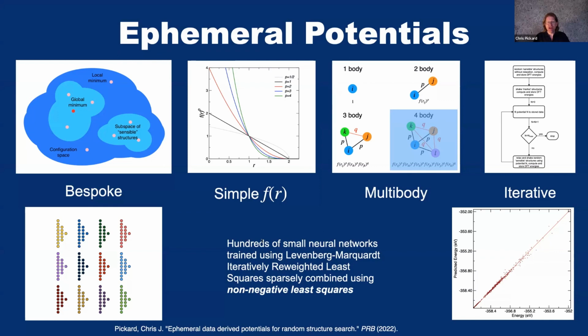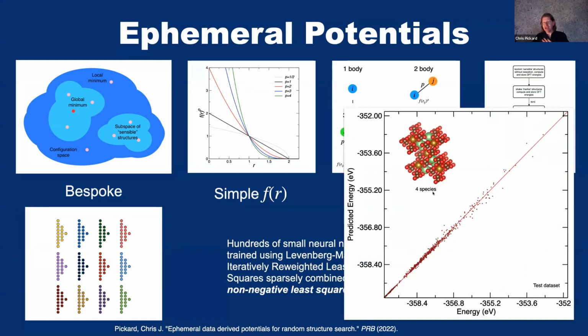And there are some details here of how we've done this. Those that are interested could read those words. They won't necessarily mean something to everybody, but we've made lots of small choices to make the potential robust and smooth. And in the bottom right-hand corner here, you can see a potential that I've trained for quite a complex system. This is a lithium iron oxalate compound. And the nature of this iterative searching algorithm is that it doesn't focus too much on the high energy regions of the landscape. It doesn't matter really what the energy is up there. We just want it to be high. But it puts a lot of its effort on the low energy structures, which we need for ranking the polymorphs or structures at the end.